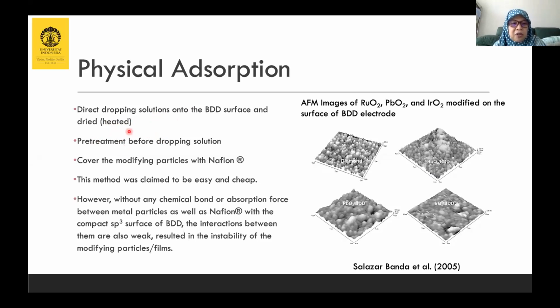Before dropping solution, we can also do a pre-treatment. For example, give some modification first to the surface of diamond, or we can also cover the surface of the particles with films like Nafion. Generally, it can give longer stabilization. But although this method is claimed to be easy and cheap, without any chemical bonds or adsorption force between the particle and the surface of diamond, the modifying film will be easy to remove.